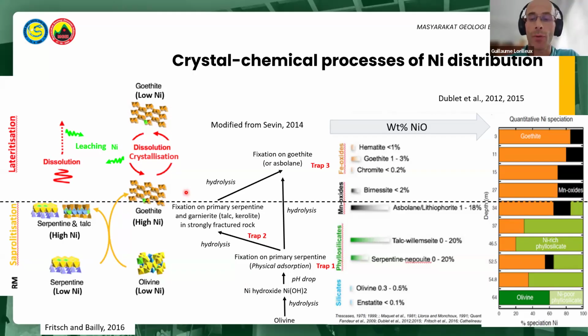The process is fully controlled by the pH front and its shape. Nickel is more strongly adsorbed at high pH values. Adsorption of nickel is significant in a narrow range of pH due to the competition of magnesium and nickel for sorption sites of goethite surfaces. The minerals having the highest content in nickel are in saprolite and the lower part of limonite, as we have already seen.